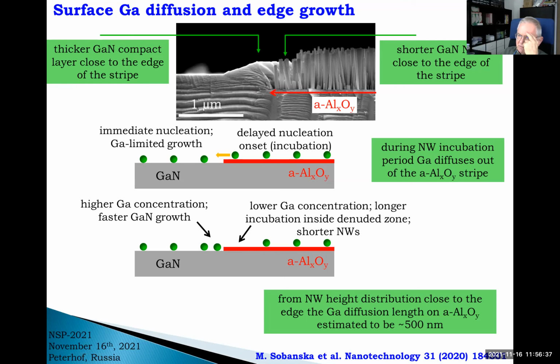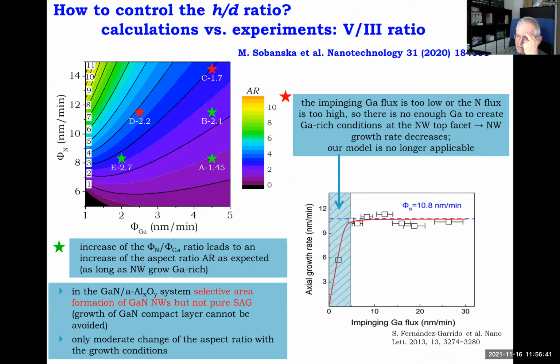Okay, this was a kind of a little bit academic exercise, because these structures, you see this aspect ratio is low, so they do not have a very practical meaning. But we can do the same when covering the side part with silicon nitride. And because we know that incubation time on silicon nitride is much, much longer than on aluminum oxide, we can choose conditions in which incubation on a mask will require something like 3 hours or 5 hours, while incubation on aluminum oxide is still at a reasonable time. So having the structures, we get perfect growth selectivity as required for application.